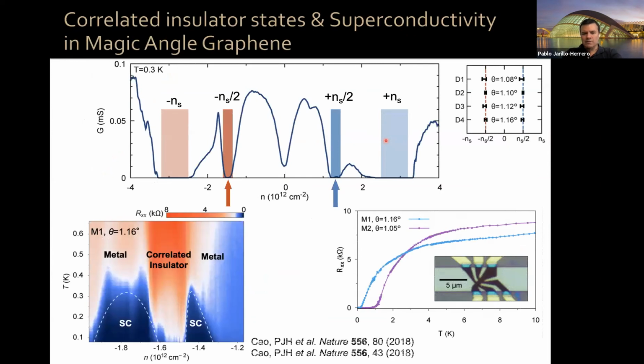Now, what my group discovered already 3 years ago is that when you put your chemical potential in the flat bands of the system, there are regions where you can reach correlated insulator behavior, and there are regions nearby where you have an electrically tunable superconductor with many similarities to other correlated materials which exhibit superconductivity. Okay, this happens all in a relatively narrow range of twist angles around 1.1 degrees. So, okay, this is what I told you about pretty much yesterday.